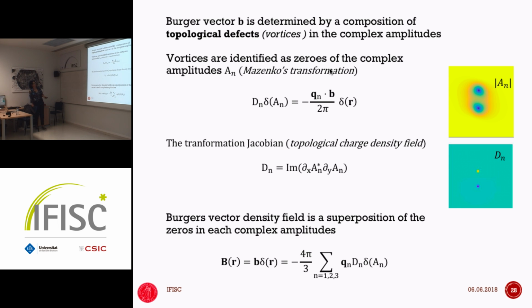So now, how do we relate the Burgers vector that we see in the hexagonal lattice to the topological defects, the topological charge of the amplitudes? The mathematical relation is through Mazenko's transformation, which is a very nice transformation when you have an order parameter and a symmetry breaking that produces topological defects. You can locate the position in real space of those defects through the zeros of the order parameter. So you go from the zero of the order parameter to the location of the defect.